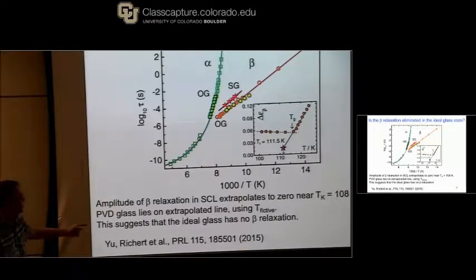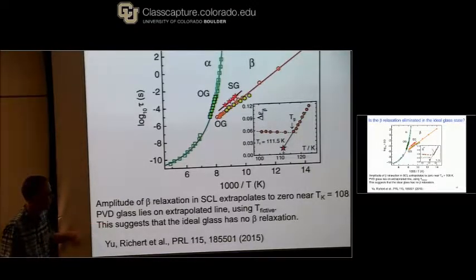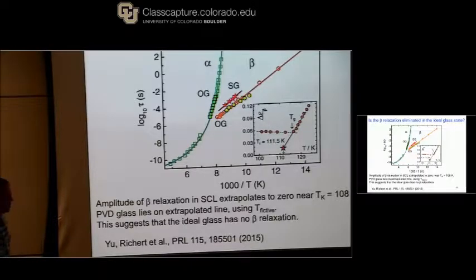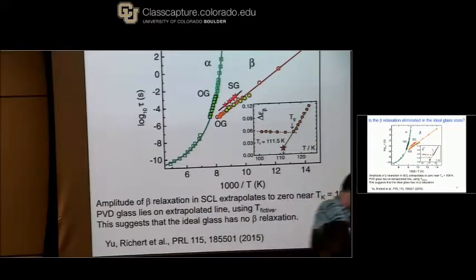So just to be clear, I'm not claiming we made the ideal glass. I'm claiming that we've moved 3/4 of the way there, and that it's fair to make a little bit of an extrapolation at this point. And if I make that extrapolation, this suggests, at least for toluene, that the ideal glass will not have a beta relaxation. That the amplitude of these secondary relaxation processes will just be completely gone, the molecule's orientation essentially completely locked in place by the very tight packing. Maybe I'm wrong, but that's what the data suggests.